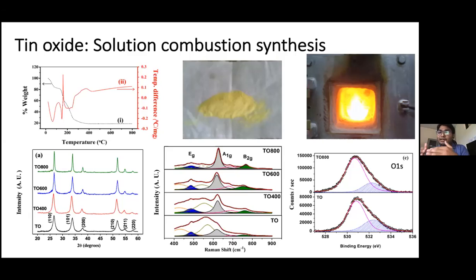You will get rid of the grain boundaries, wherein most of the defects can occur. You will get rid of the vacancies, because the structure will try to refine itself. So then I annealed these samples at different temperatures.